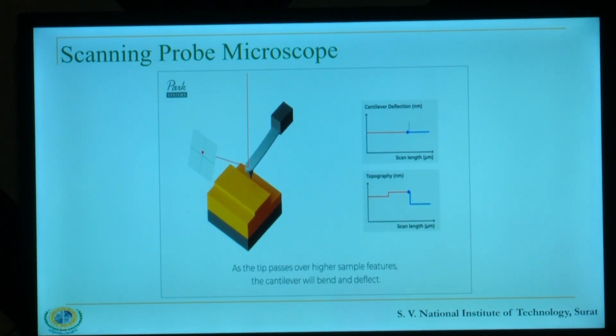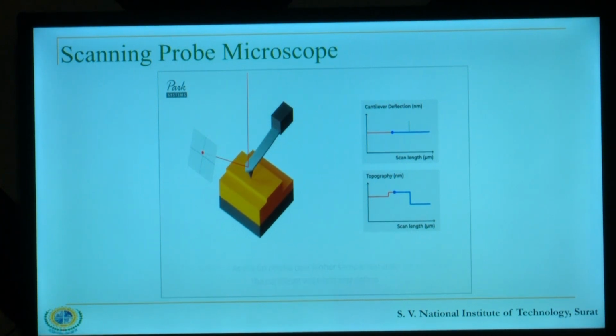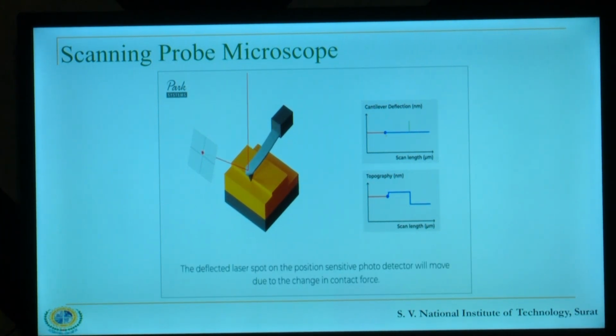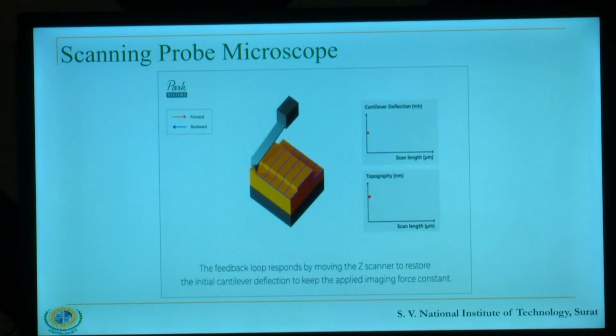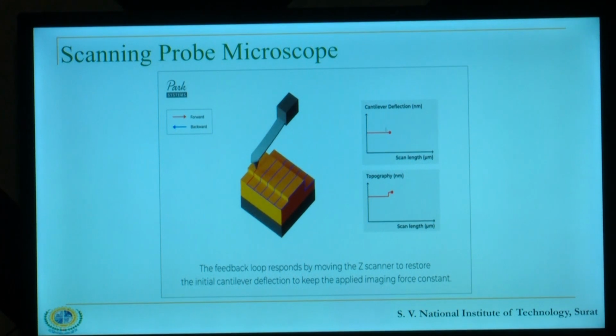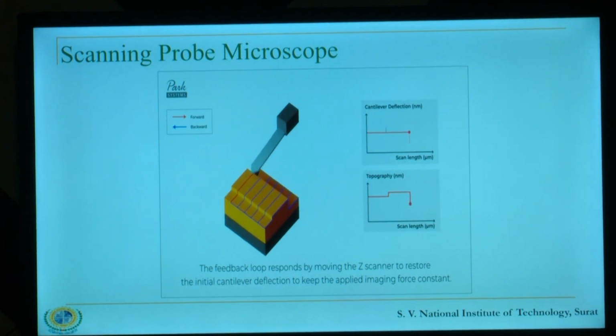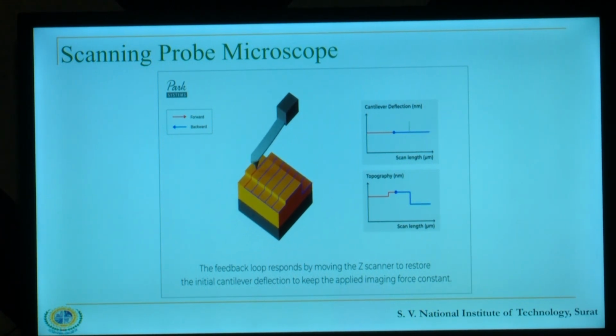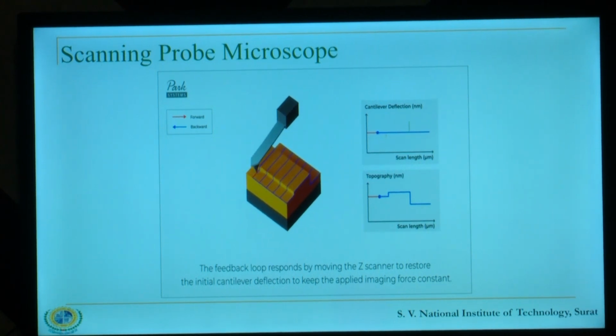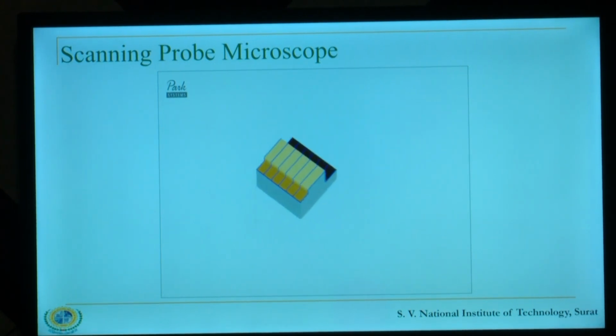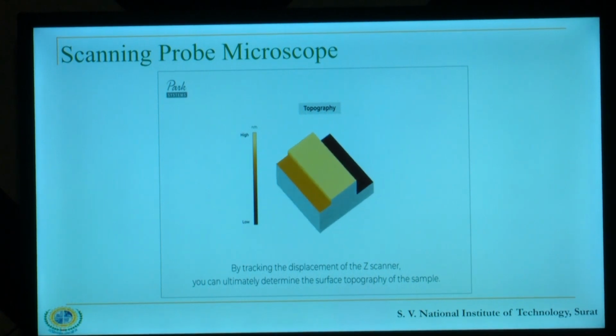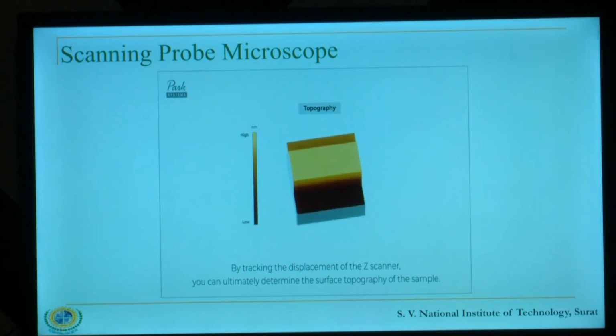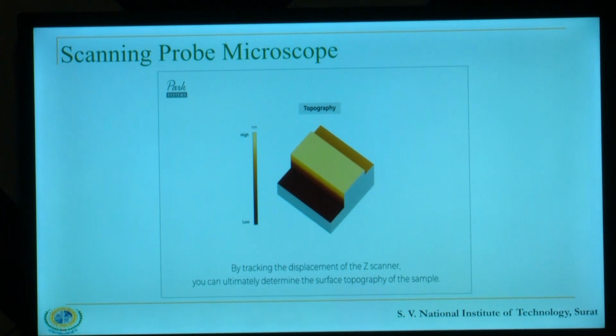So, here the thing is it touches the surface. The deflected laser spot on the position-sensitive photodetector will move due to the change in contact force. The feedback loop responds by moving the Z-scanner to restore the initial cantilever deflection to keep the applied imaging force constant. By tracking the displacement of the Z-scanner, you can ultimately determine the surface topography of the sample.